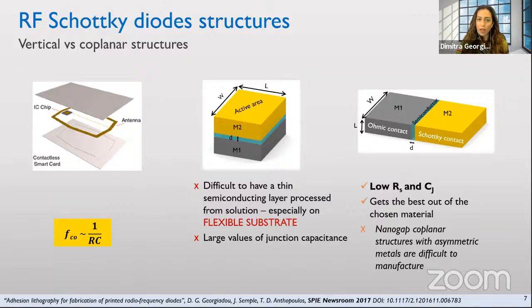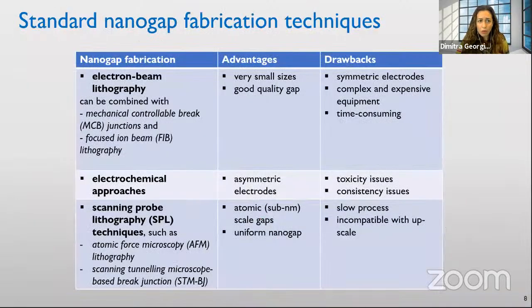So at the same time, we can address both a decrease in resistance by choosing the material and in capacitance by changing the geometry, and also be compatible with flexible substrates. However, the greatest challenge here is that to fabricate these nanogap coplanar structures, especially when we want to use asymmetric electrodes to be able to fabricate Schottky diodes, the actual methods to do that, the fabrication techniques, are not really scalable. And I'll come to that right away.